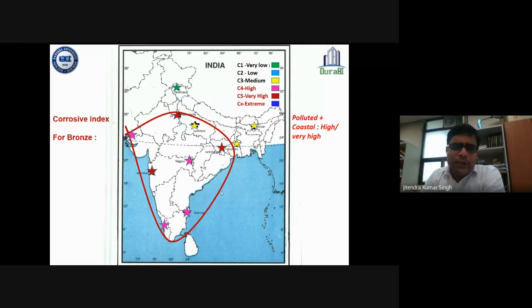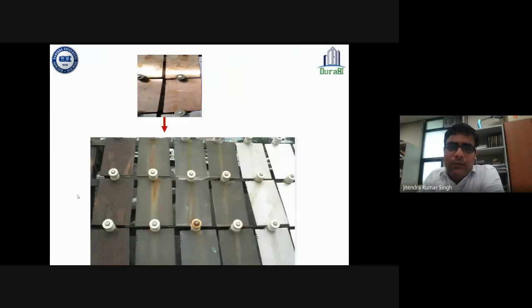Then brass we have exposed, so you can see in the case of brass, here Nagpur, Chennai, and Trivandrum have a high corrosion rate. And you can see New Delhi, Lucknow, Kolkata is medium, and Jorhat is also medium. But Palanpur doesn't have any pollution. It is a hill area, so there is no pollution. If there is no pollution, the corrosion is very less. It means pollution is influencing the corrosion. Also, you see the brass has a very low corrosion rate in Palanpur.